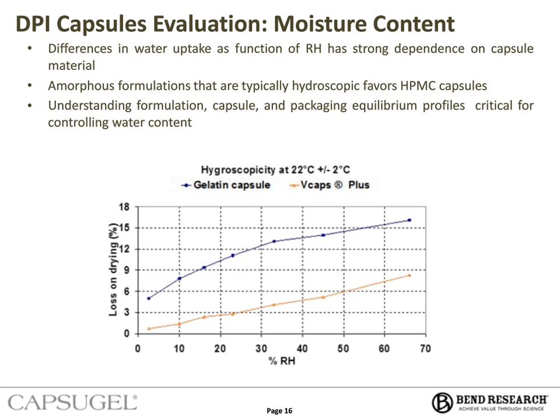In both cases, there is a possibility to have capsules with a lower water content, which would have a lower water activity, and we could target something around 0.3, which would give you HPMC capsule where the moisture can be as low as 3% and below. Obviously, if the capsule contains low amount of water, the risk of moisture transfer to the fill is considerably reduced.